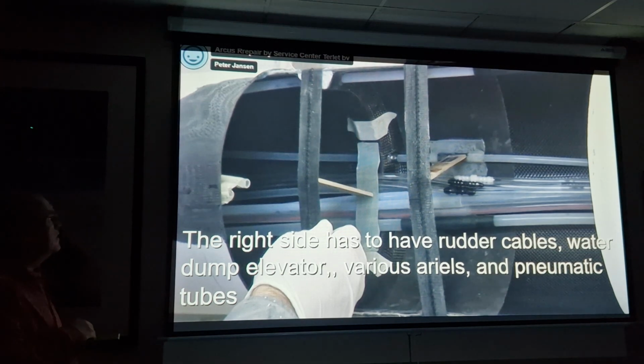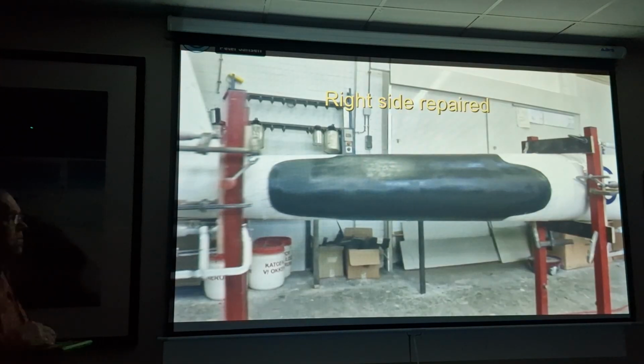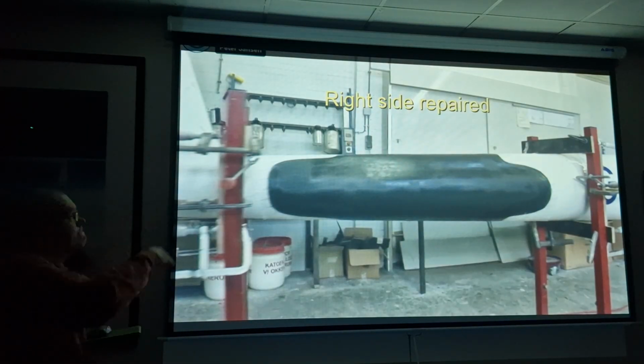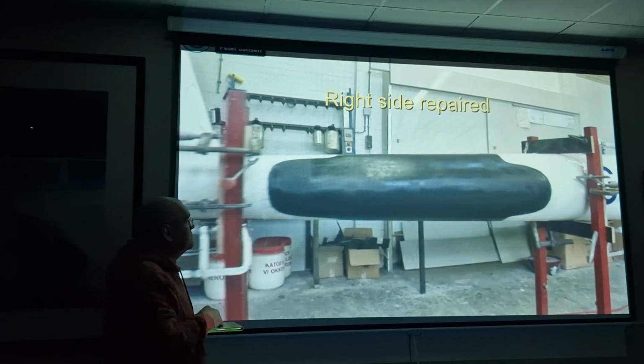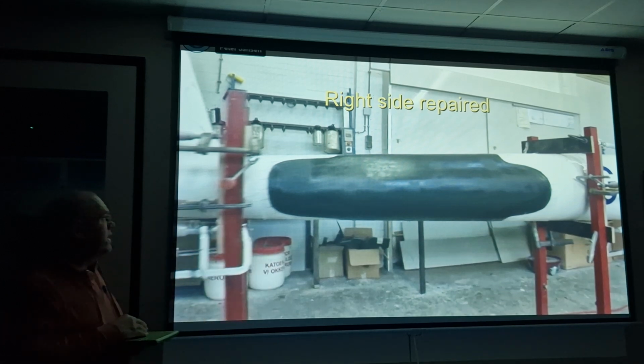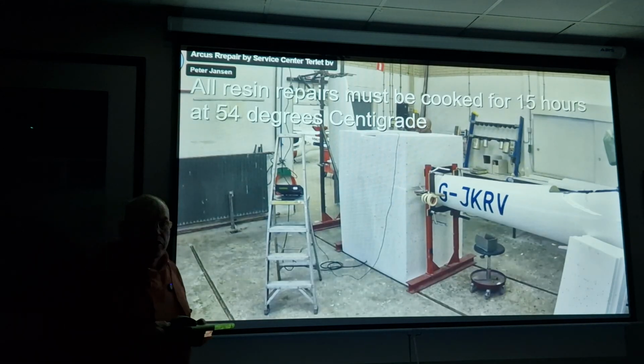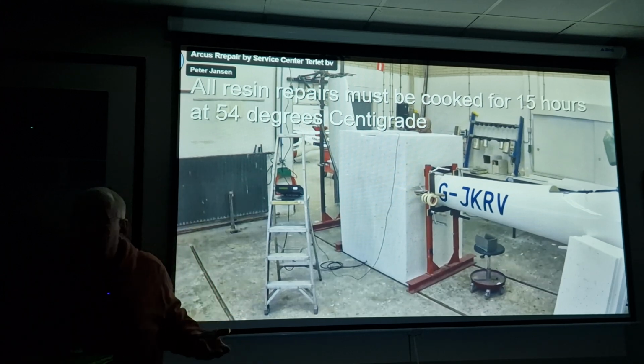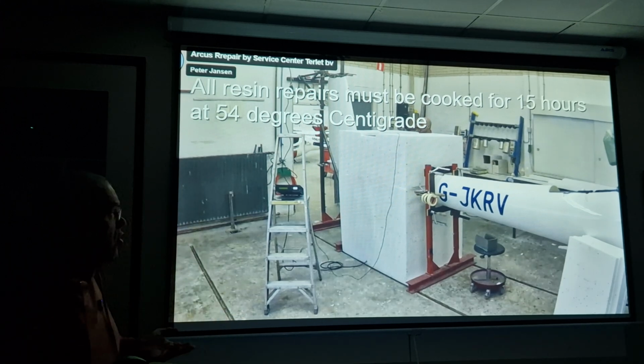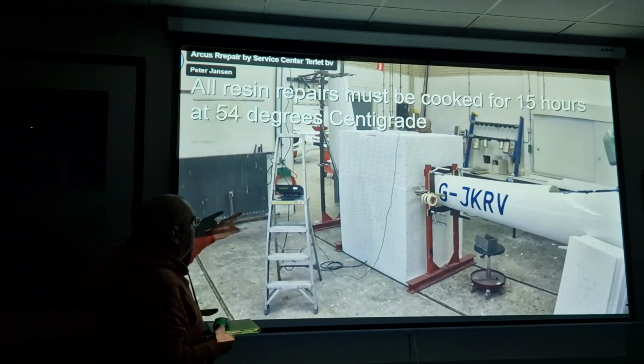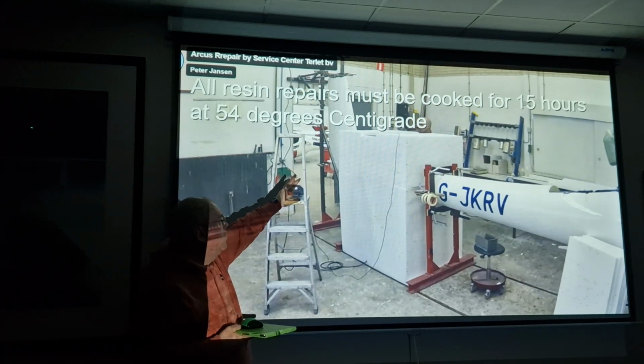But then they literally slap the male side back in there, splice it in, and then they have to cook it. And when you cook it, you don't cook the whole glider because you don't have the jigs for the whole glider. That's all. So you just cook the repair. When you buy a new back end, it actually comes already cooked. So all you have to do is cook the repair.